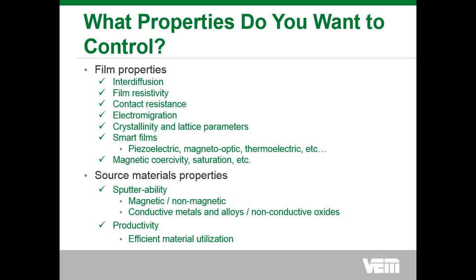At the same time, controlling those properties, the thin film engineer needs to be sure that the source material can be sputtered. And really the challenge there is, if it's a magnetic material, how do I make it less magnetic so I can sputter it? If it's a conductive material or a non-conductive material, I need to think about how I can take a non-conductive oxide material, for instance, and make it conductive enough to sputter using some of the various rectifications. And at the same time, as the thin film engineer goes from development into production, they're looking for efficient use of their materials, or better material utilization.